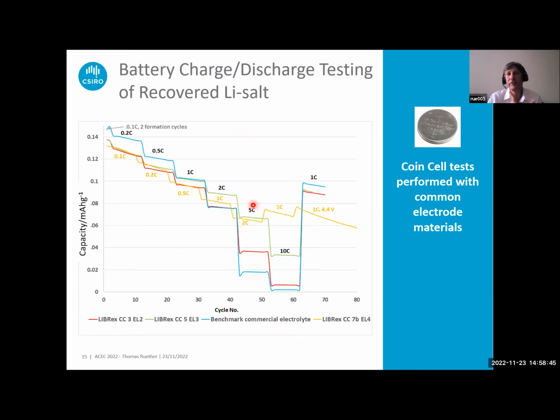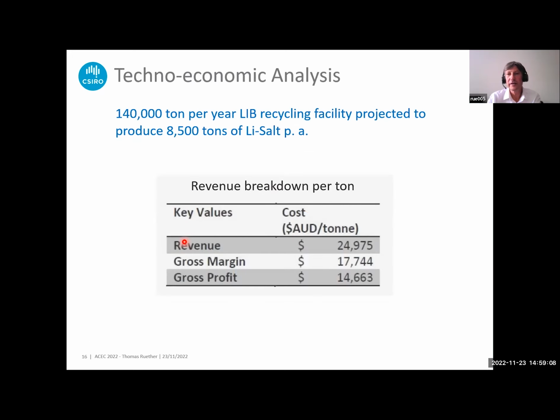So this is the plot for the battery testing. The blue curve is commercial electrolyte, and the other traces is our system generated with the LiPF6. It stacks up quite well. There's slight differences because the commercially available electrolytes use secret ingredients, which we don't really know of. And techno-economic analysis tells us that the revenue could be $25,000 per ton of the LiPF6 and with a gross profit at around $14,700.